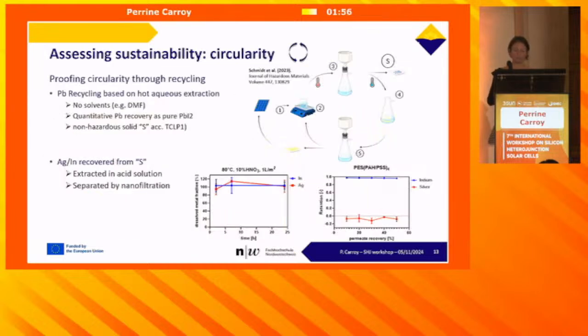And we have a team in Basel that tries to recover materials from the perovskite, so from hot water extraction to extract the lead iodide, and then from the solid here, it's full of indium and silver. They can recover it with acidic extraction and then can separate them with nanofiltration.